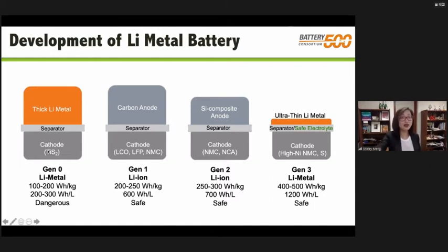Right. So in the 1970s, when Professor Whittingham built the first lithium metal batteries, the cathode had no lithium in it. It's titanium disulfide. So for this reason, he needed to put a very thick block of lithium metal on the negative electrode side. Our situation is completely different. We have high lithium containing lithium cobalt oxide, lithium iron phosphate, or lithium nickel manganese cobalt oxide.